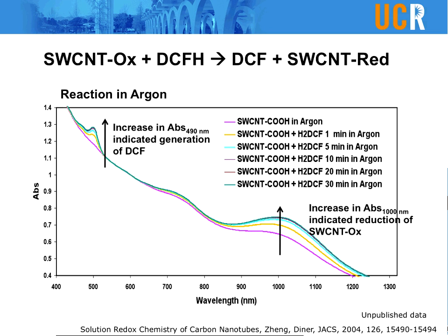How we find out the carbon nanotube itself can be the oxidation agent: we use UV-Vis spectroscopy, so it's ultraviolet-visible absorption spectroscopy. Literature pointed out that carbon nanotube actually can oxidize reductants, small reducing agents. And they observed that kind of oxidation by IR spectroscopy, but they did it in atmosphere. So they attributed it all to a reaction catalyzed by carbon nanotube, and the oxidation agent is oxygen.